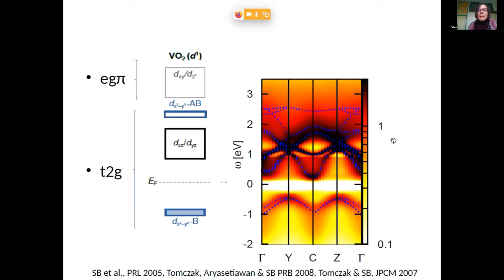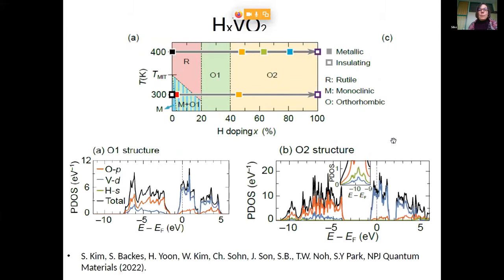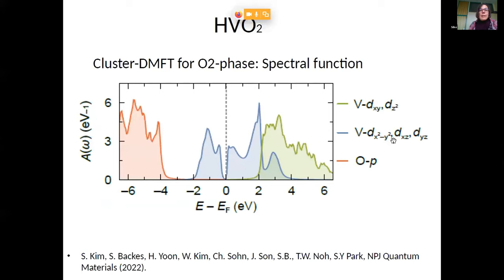And so this is what we used in the hydrogen doped case. Here we were treating the A1G orbital within the scissor approach borrowed from the pure compound and then just analyzed for the remaining EG pi orbitals what is happening. And I think this is a nice way to move forward, because of course it makes things much more efficient, also in view of larger systems. So I guess this is your point, right?